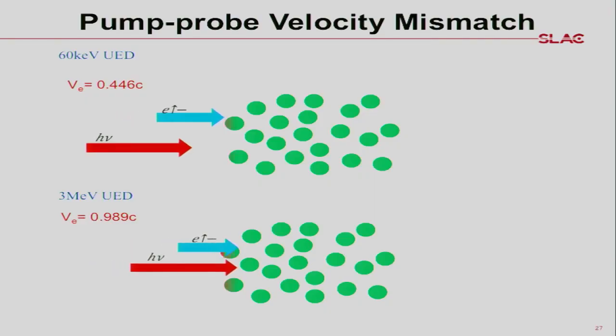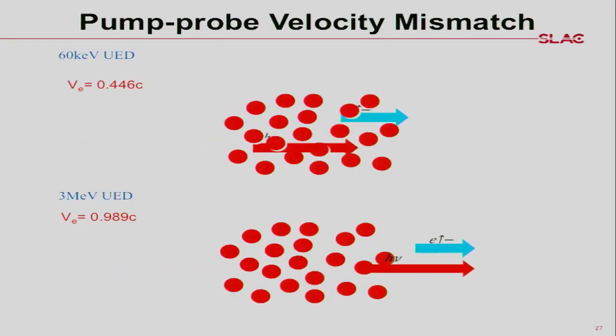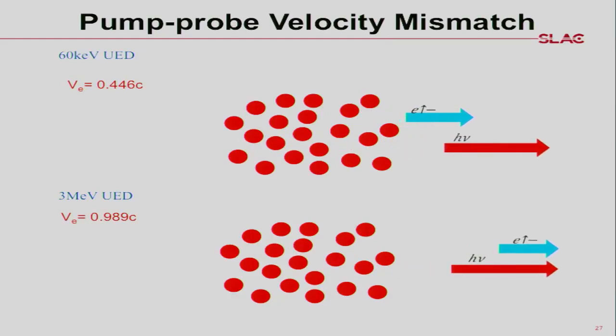Another limitation for ultra-fast electron diffraction is the so-called velocity mismatch. Basically, you have a photon which moves at the speed of light, and you have electrons that move slower. At low energy, because of the mismatch, you get the temporal resolution limit. So to eliminate this, you have to really go to high energies.